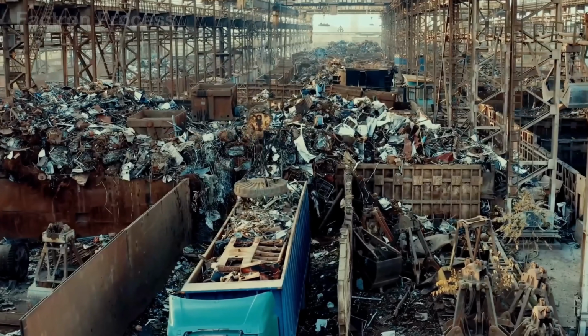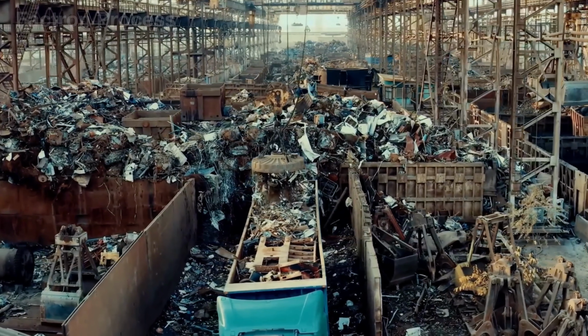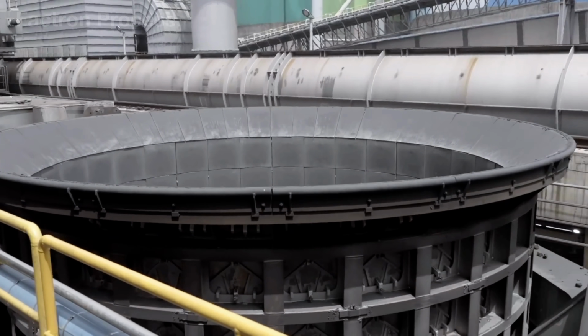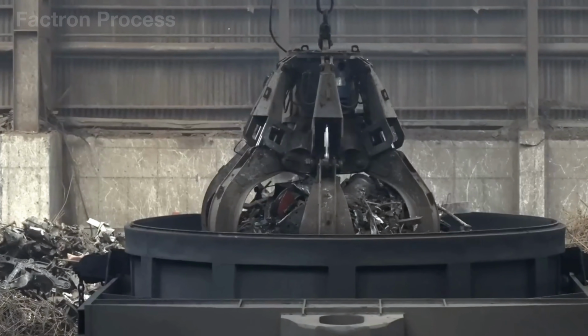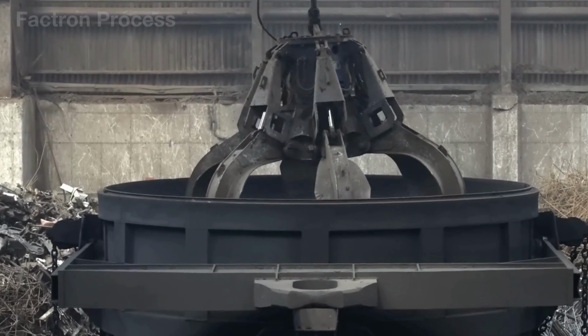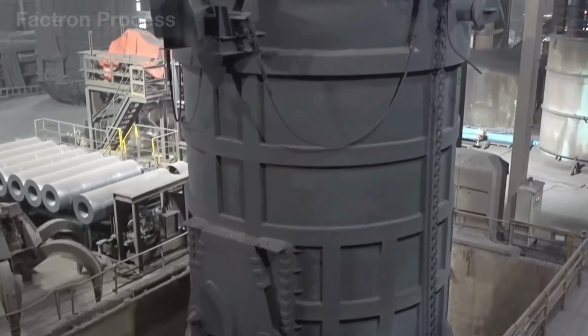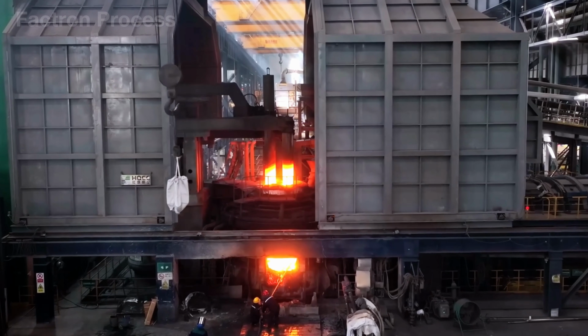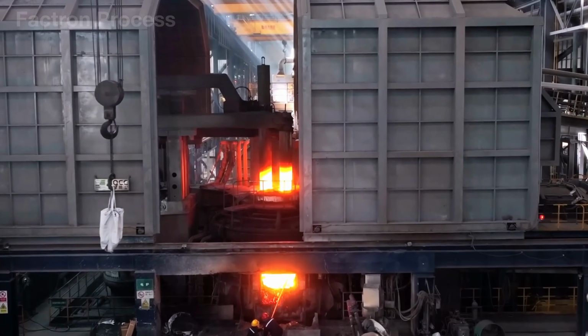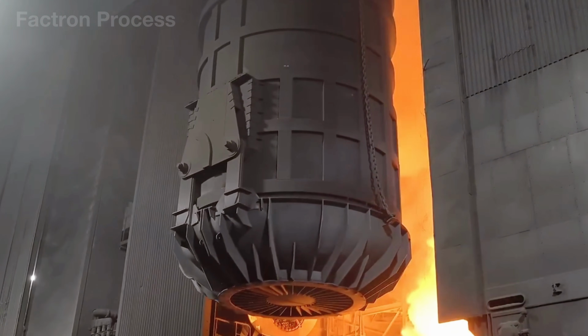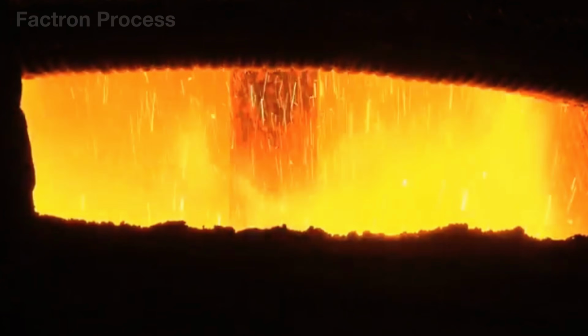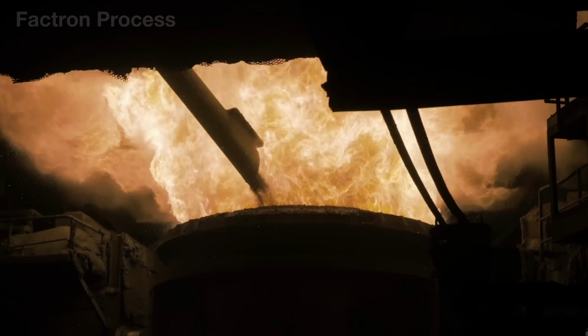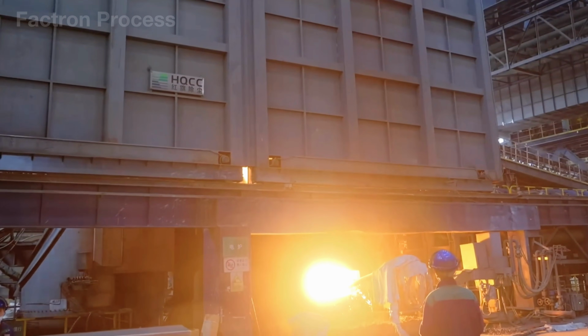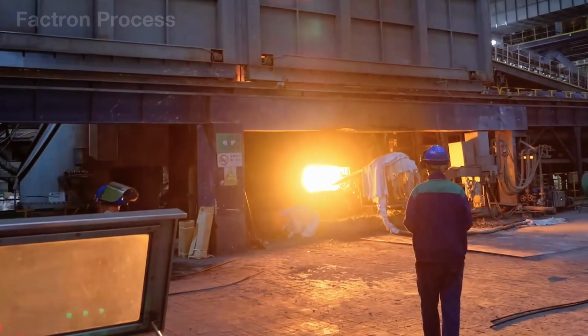The journey of automotive recycling now enters its brilliant metallurgical core. Clean shredded steel is poured directly into an ultra-high power electric arc furnace. 3 massive graphite electrodes are then lowered into the furnace, releasing an immense electrical current of up to 80,000 amps. This creates a blinding plasma arc like artificial lightning, with a core temperature exceeding 10,800 degrees Fahrenheit, rapidly melting the solid scrap into a pool of liquid metal at more than 2,900 degrees Fahrenheit.